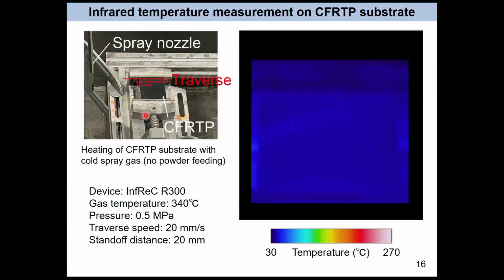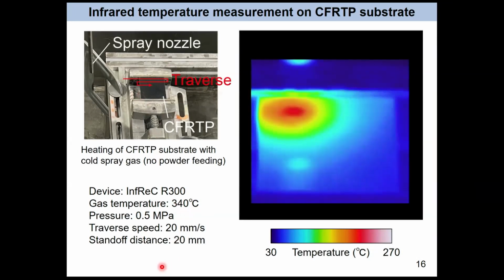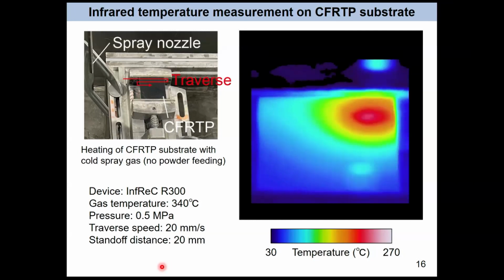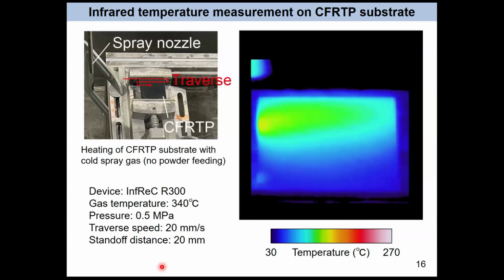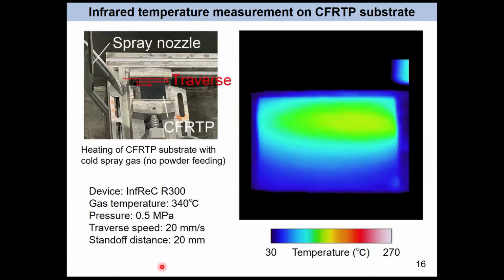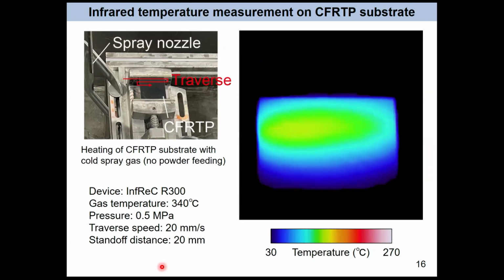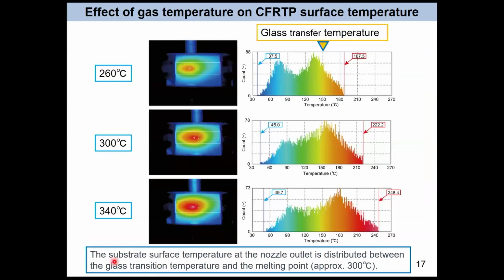In this experiment, we just exported hot gas at 340 degrees, with no powder feeding. We just exported the gas onto the substrate and measured the surface temperature of the CFRP. This condition is the same as the cold spray condition. So like this, the nozzle sweeps over the cold CFRP, and we measure the surface temperature distribution of the CFRP. Now, this slide shows the 260 case, then 300 and 340.